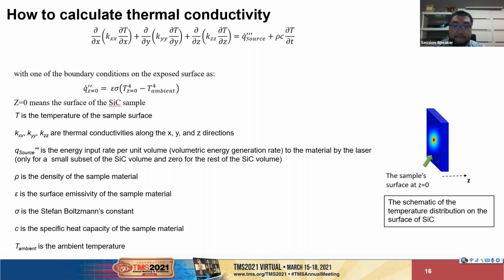You can see in this equation, the boundary condition is at z equal to 0, which means the surface of silicon carbide. T is the temperature of the sample surface, and Q source is the energy input rate per unit volume. Rho is the density of the sample material, epsilon is the surface emissivity, sigma is the Boltzmann constant, C is the heat capacity, and T ambient is the ambient temperature.